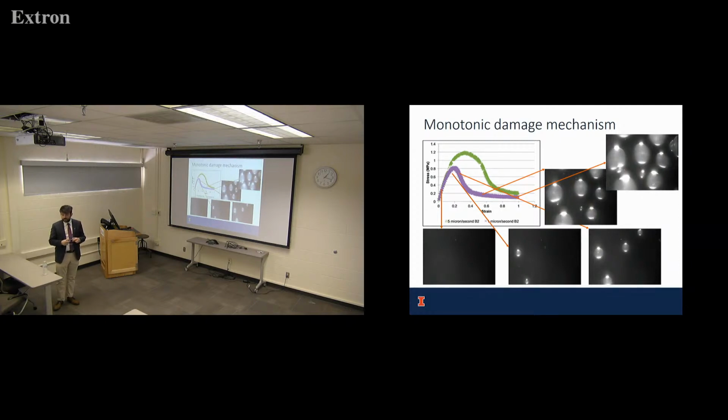So we do define it as cohesive failure, but what ends up happening within that film, it's then created a cavity that's not a two-dimensional cavity, it's three-dimensional. So there's just such a thin film of binder at the top that you can actually see the back of the plate through that binder. It becomes transparent enough that light can scatter behind it. Were you able to verify that there was binder?